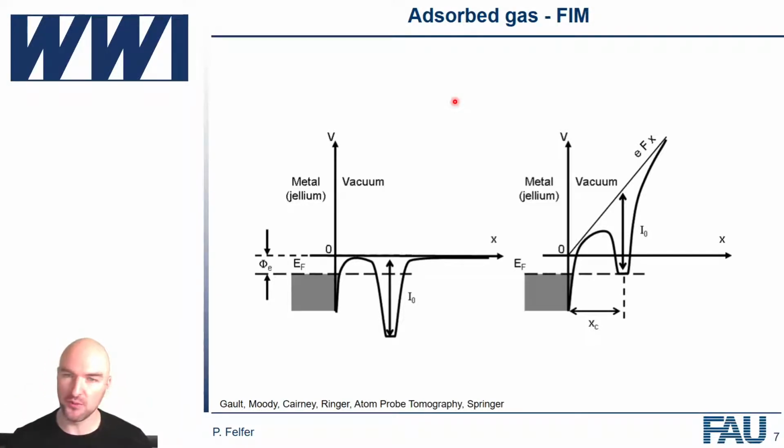And the way it works is a little bit different. We need to move the potential, the level of the highest occupied molecular orbital, or atomic orbital in this case, so high that there is an energy gain for this electron to tunnel into the solid. Because they're not electrically connected, it can only tunnel inside.